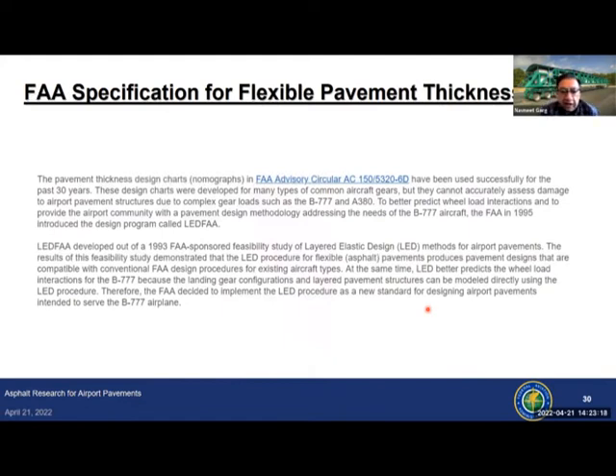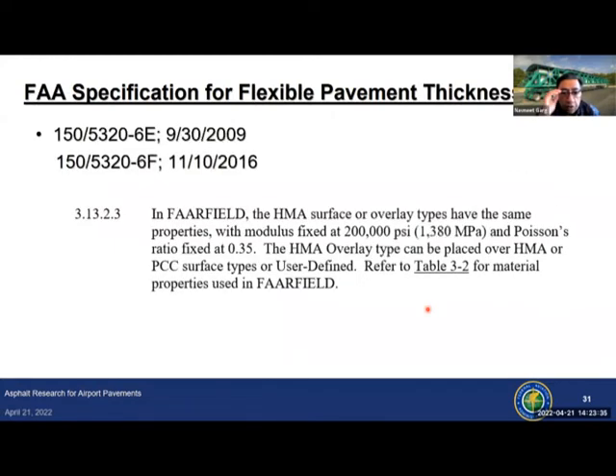And then in 1993, when the Boeing 777 came out, if the 777 was in your traffic mix, you had to use LEDFAA to do thickness design. And LEDFAA was based on layered elastic analysis. So the modulus value for the asphalt surface layer was fixed at 200,000 PSI, and the assumption was that this is the modulus of asphalt mix at 90 degree temperature. Poisson's ratio was fixed at 0.35. And for P-401, or the stabilized base, the modulus was fixed at 400,000. The reasoning there was that the asphalt stabilized base is below the surface, so pavement temperatures are going to be lower, so the modulus will be higher.